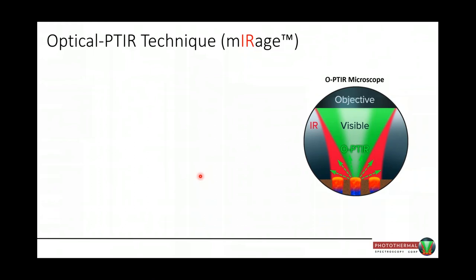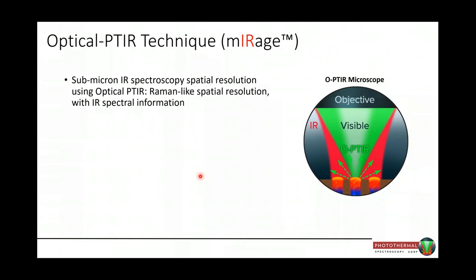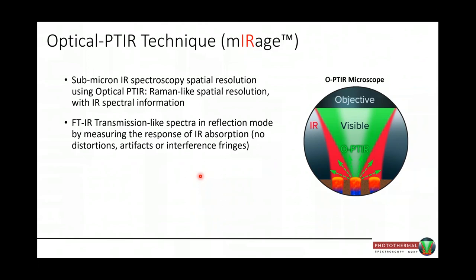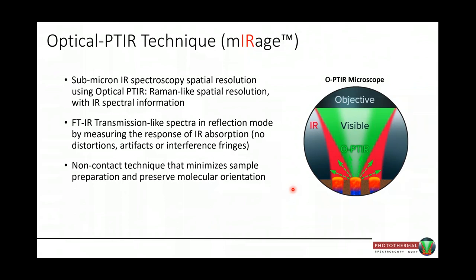So the way the technique works, you have sub-micron IR spatial resolution and spectroscopy using optical photothermal infrared spectroscopy. You get Raman-like spatial resolution with infrared spectral information. The spectra look like FTIR transmission spectra, even though they're measured in reflection, without any distortions or artifacts or interference fringes. It's measured non-contact, and that minimizes sample preparation and preserves the molecular orientation. And the spatial resolution is not dependent on the IR wavelength.